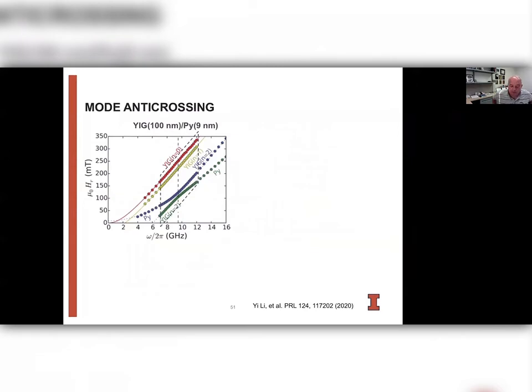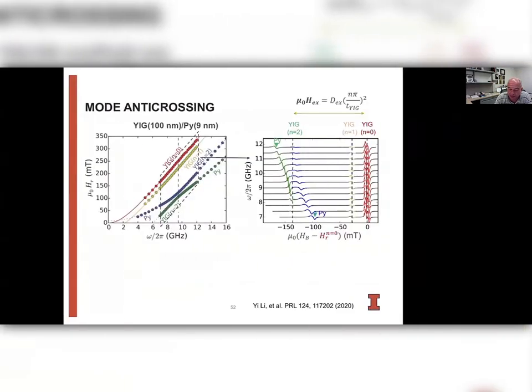So in order to better see this crossover, what we'll do is we replot all these resonance modes, but reference them versus the homogeneous ferromagnetic resonance mode in the yttrium iron garnet. So this is what you see here. Of course, the yttrium iron garnet ferromagnetic resonance is then by definition always at 0, even for different frequencies here. And the spin wave modes of the yttrium iron garnet are always at a fixed relative field with respect to the FMR here. And so we see the permalloy mode dispersing nicely through the yttrium iron garnet. And in the crossover regime, we see two well separated individual resonances.